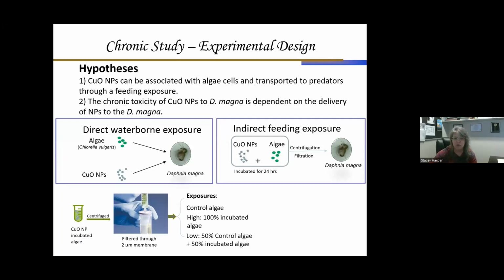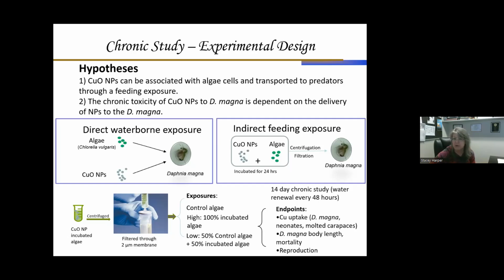And our exposures were basically a feeding of just algae alone. And then we had a high concentration where we did this incubated algae here. And then we did a low one where we did half and half, just regular algae, non-exposed, and half of the incubated algae. And we did these over 14 days, and we renewed the water every 48 hours. And we looked at copper uptake into the Daphnia themselves, into neonates that they produced during their exposure, and the molted carapaces. We looked at things like body length and mortality and reproductive success.